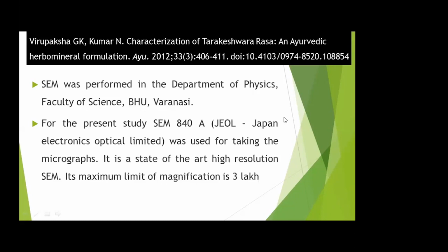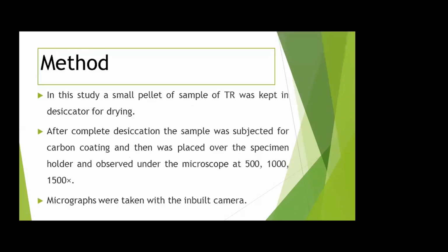The maximum limit of magnification of this instrument was found to be 3 lakh x. In this study, a small pellet of the sample, Tarakeshwara Rasa, was kept in a desiccator for drying. After complete desiccation, the sample was subjected to carbon coating, and then placed over the specimen holder, and observed under the microscope at 500, 1000 and 1500x.